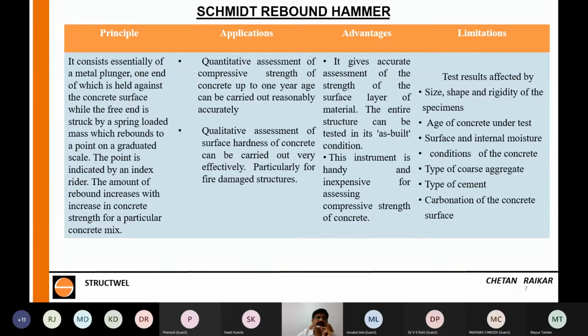These are the applications: quantitative assessment of compressive strength of concrete up to 1 year. Because why? When I say 1 year, it's the carbonation of concrete that affects, it starts affecting after 1 year, 2 years, 3 years, depending on which city the structure is. A dry city like Pune or Nagpur will have much slower rate of carbonation, whereas a moist city like Mumbai, with a very high humidity, will have a lot of challenges. It gives advantages. It is very accurate. It's inexpensive. It's a very short and portable, handy equipment. It can be taken to any place.